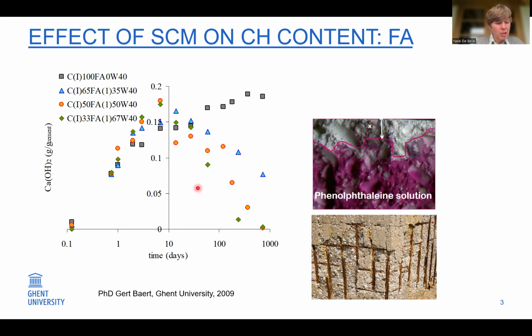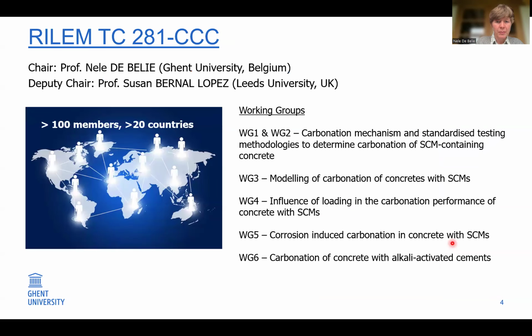Here in our previous research, we have shown that, for instance, in mixes with increasing amount of fly ash from 0 to 67% of the binder content, at early ages, there might be an increased amount of Portlandite production due to the stimulating effect on the clinker reaction. But after about 2 weeks, the pozzolanic reaction kicks in, and after more than a year, it can be that the Portlandite content goes down to 0. Hence, there can be an increased risk of reinforcement corrosion induced by carbonation.